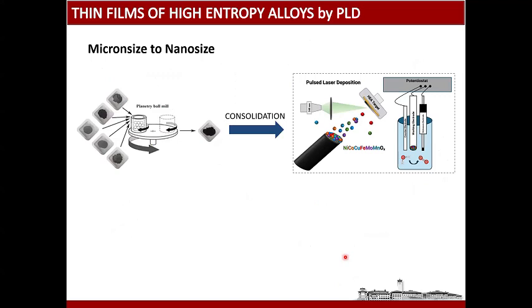So then, since size is important here, we used micron size particles in that previous example, and then we tried to increase the size of the particles by doing pulse laser deposition, and this is also a direct synthesis of thin films of high entropy alloys from bulk materials. So we again ball milled, then consolidated the high entropy alloy, and then we have this high entropy alloy target, and over there we use this UV pulse laser, nanosecond pulse laser, and this pulse laser etches the atoms from the surface of high entropy alloys, and then deposits these atoms on the surface of the electrode.